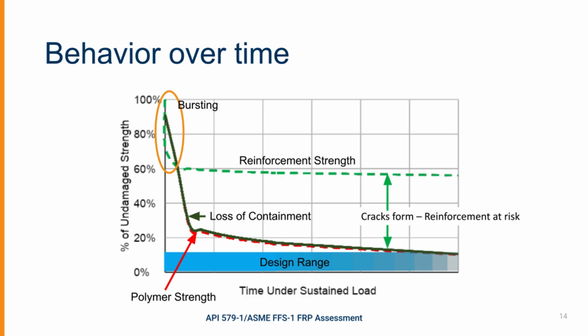Over time, and I'm actually showing a chart here, the behavior over time is that if we apply a very, very short but large load to FRP, it will fail or burst after a very short period of time. As the time extends with lower loads, we start to get cracking or fracture at different levels. And this chart actually shows that we will lose containment. For instance, a pipe will leak, a vessel will leak, the polymer will crack at much lower loads than the reinforcement will. And in fact, that's the thing that we're working to.